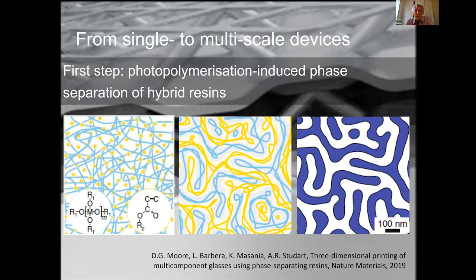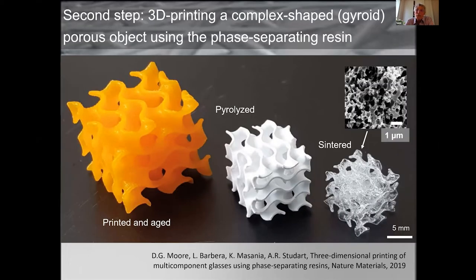What the team did was to start with a blend of two different monomers in a miscible state. Then they photopolymerized the two components. When they polymerize, they become non-miscible, so they demix. Then you can remove one of them, just like people do when they prepare Vycor glass, one of the model materials, which is a favorite of people doing porous material science. And with this phase-separated material, with a pore size in the nanometer range, they 3D printed a kind of gyroid structure, which I showed before, which introduced a second scale